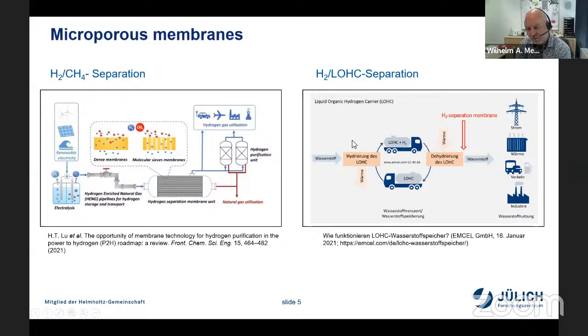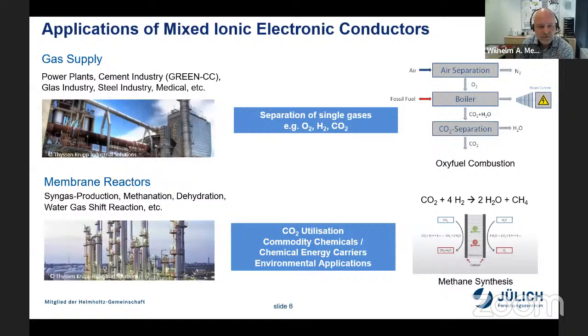But now I will switch to the main part of my presentation, the so-called ionic conductors. My focus today is on mixed ionic electronic conductors. If you look at a membrane which is used in an electrolysis, you have only ionic conduction, and then you have an outer circuit, which in principle is also the driving force for the diffusion of the ions through the membrane. But if you have a mixed ionic electronic conductor, your driving force is the gradient of partial pressure of the gas, which is permeating on both sides.